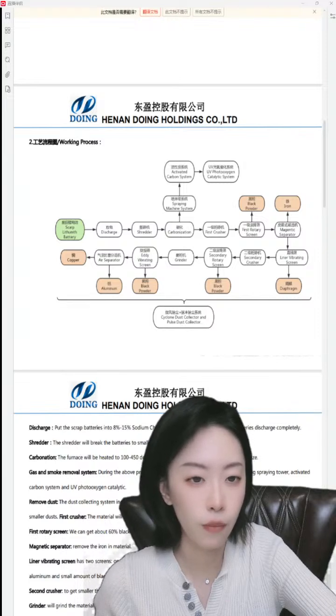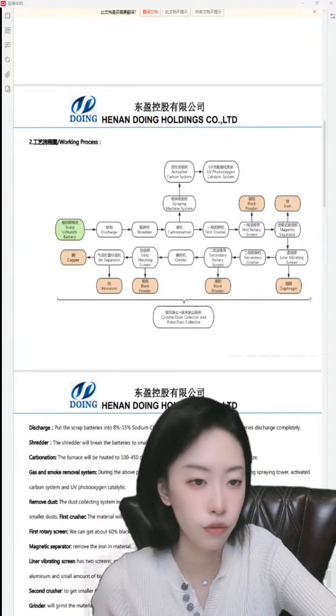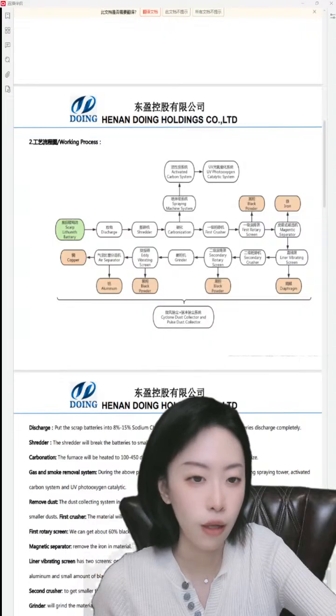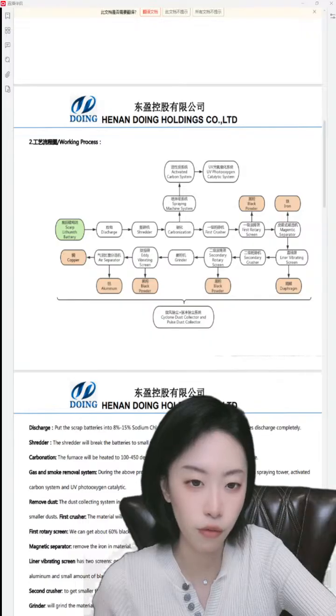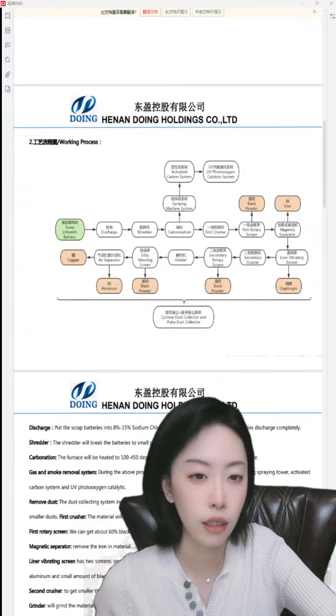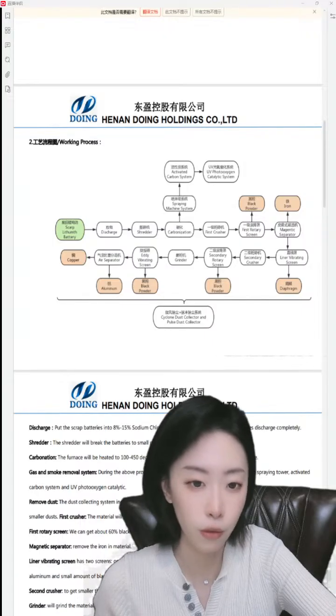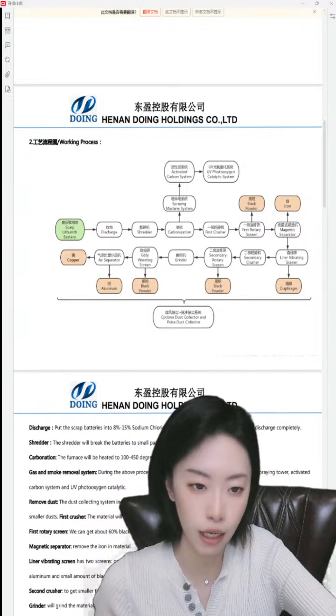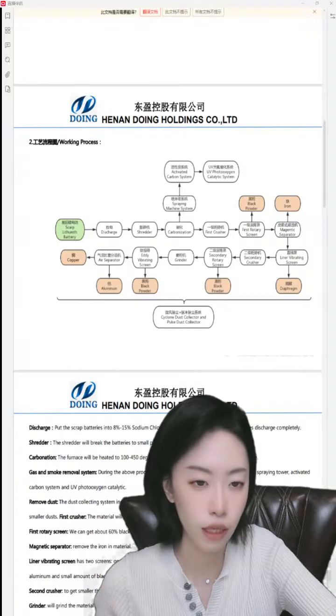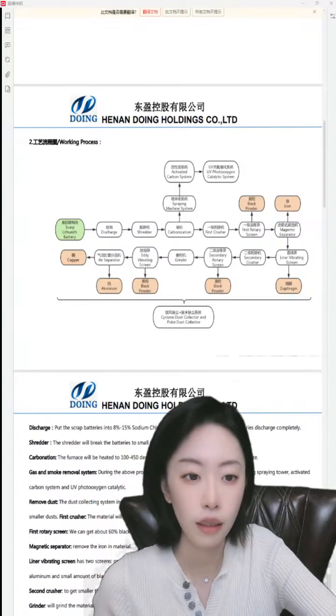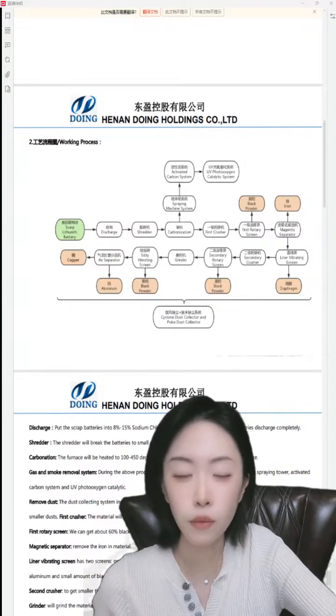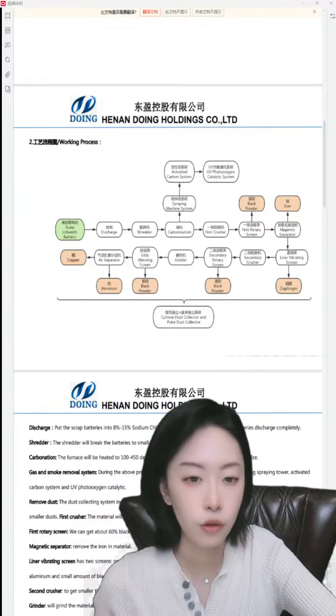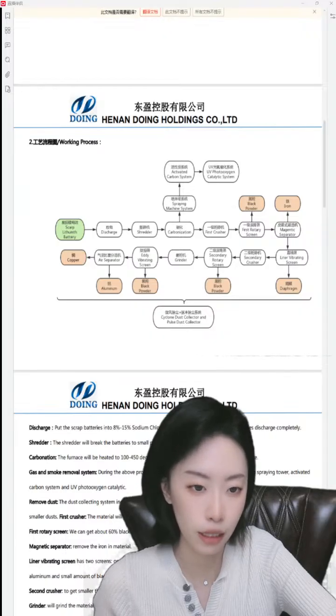The crushed material from the first crusher is sent through the air transportation system to the fully sealed rotary screen for screening through the 120 mesh screen surface rolling rotary screen, so that the qualified material as a battery powder is discharged through the rotary screen holes, and the black powder here can be recovered about 60 to 70%. This machine is the first separation machine, and the length is 6 meter. And then we will use the belt conveyor to transport the material into the magnetic separator, that is, to separate the iron.